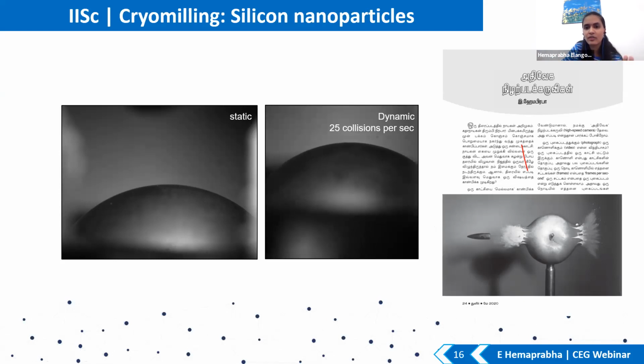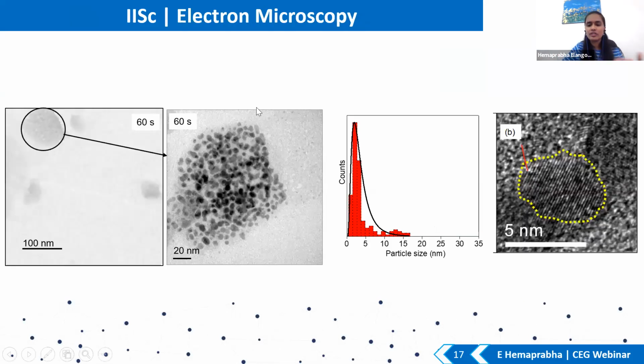Similar to that, I will give you another example. I was telling that I got nanoparticles, but how do I know I really got nanoparticles unless I see them? So there is a different field, which has now become a big field, electron microscopy, using which we can image particles of very few nanometers. All these images were taken by me, and you can see here a bunch of particles. When I take a close look, the particles were less than 20 nanometers, because this is 20 nanometers, and you see all the particles were less than that. And I have particles of about 2 nanometers, and I can even see how the atoms are arranged at this scale.